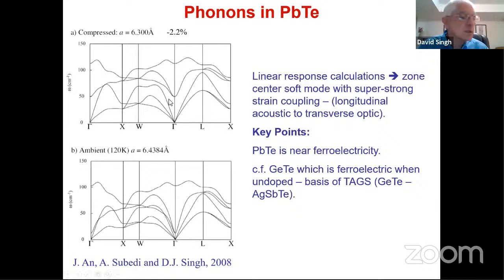But this other one with these low frequency vibrations moved to higher energy. And that means that when you compress the material, there's a pretty strong interaction between that compression and these vibrations of the crystal lattice. Okay, we compress by 2% and it moves quite a lot. And that must be an anharmonic coupling. And so what it means, remember that this one that carries the heat is a compression wave. It means that there's a lot of anharmonic coupling between this compression wave and these vibrations that correspond to the near ferroelectricity of lead telluride. And so what we concluded from that is that a likely reason for the low thermal conductivity of lead telluride, remember kappa is in the denominator of ZT, is that this ferroelectric mode is strongly coupled to the longitudinal acoustic branch, and that gives the low thermal conductivity.